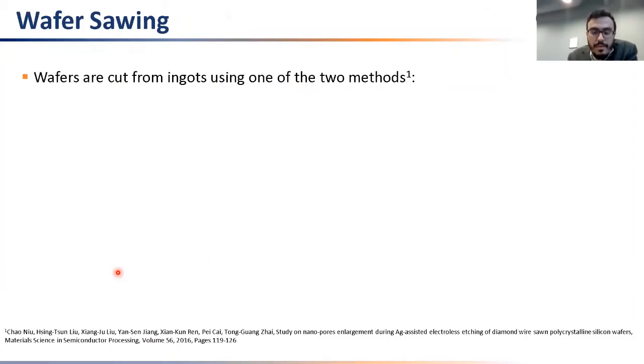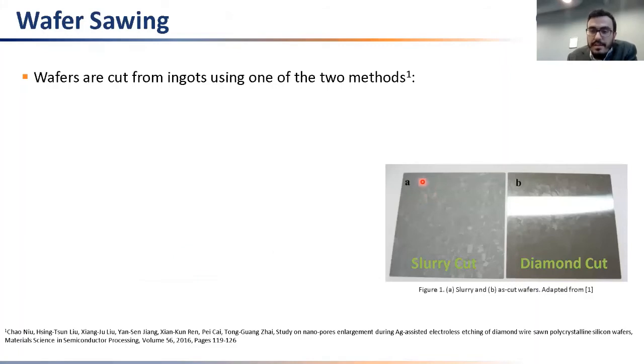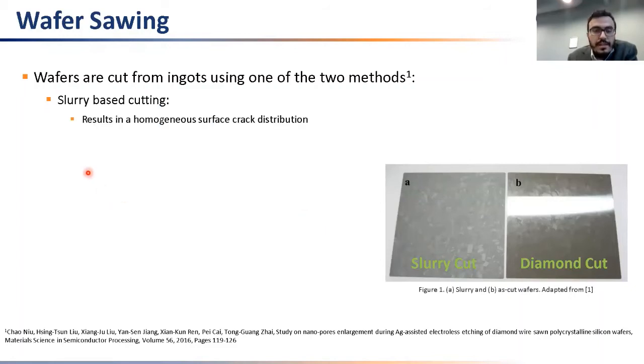So the wafers that we are using in our factory and in the photovoltaic industry are cut from ingots using two methods. One you can see here is multicrystalline wafer with slurry cutting and diamond cutting. Slurry cutting means that you are using a cutting fluid, and it results in a homogeneous surface crack distribution and kerf loss. You have a high kerf loss in this type of cutting, and you can see that you are having a rough surface and there is no reflection from the surface.